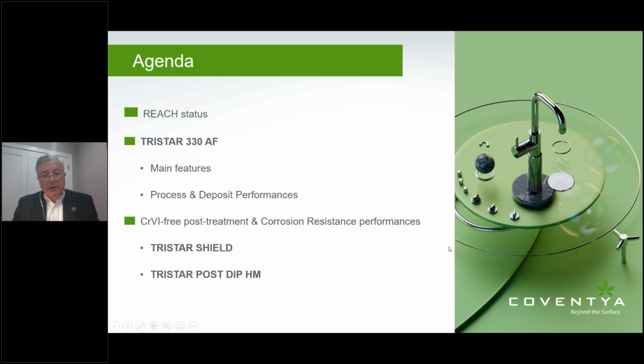It's interesting that when you look historically, the modern period of trivalent chromium plating is really said to have begun with a series of 4 patents in 1927 to 1929. So these were the first systems. The basis of those technologies were crystalline chromic acid, chromic chloride actually, in various salt forms, and they used soluble chromium anodes at the time. Basically the chromic acid was formed at the anodes and was reduced with oxalic acid and hydrochloric acid to make the trivalent chromium. So we've come a long way since then.